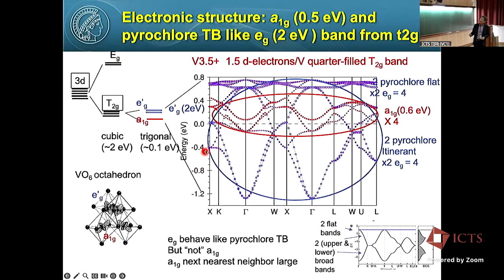And here is the band structure of the vanadate. As I said, vanadium is octahedrally coordinated, right? Because of octahedral coordination, the d orbitals split into the EG and the T2G. The T2G orbital contains 1.5 d electrons because it's a 1-to-1 ratio of 3d1 and 3d2. And in reality, there is a small trigonal distortion on top of the octahedron, and the trigonal distortion splits the T2G into a doubly degenerate EG prime and an A1G singlet.